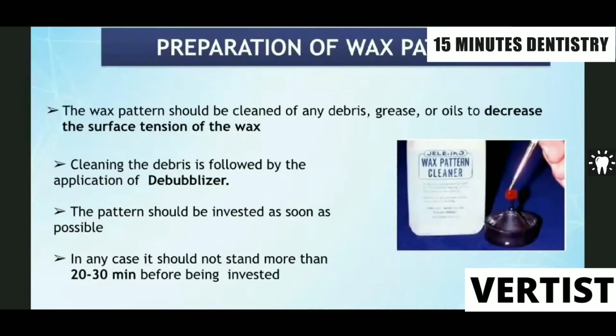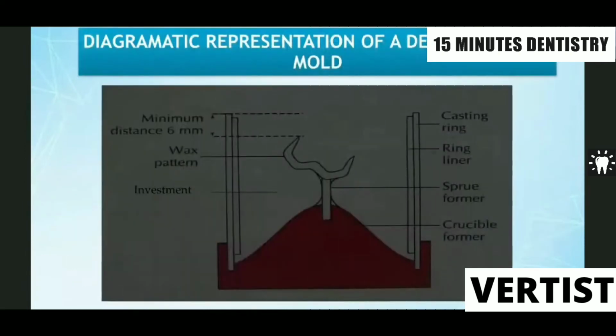Now let us go to the wax pattern. When it is prepared, it has to be first cleaned, and it should be invested as soon as possible. Within how long maximum can you afford to keep the wax pattern without investing? It is not more than 20 to 30 minutes before it is invested. This is a very, very important diagram. So please make it a point to draw this diagram whenever there is scope and a question is asked on it, explaining the different parts of the